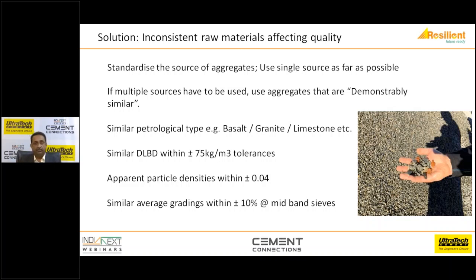If you need to go for multiple sources, I would advise going for 2 or a maximum of 3 sources. Ensure that they are of the same petrological type. The dry loose bulk density should be within plus or minus 75 kg per meter cube tolerance. The apparent particle density should be within plus or minus 0.04. And the average gradings should be within plus or minus 10% in the mid-band sieves. Apart from this, make sure that you don't have a high degree of variability in the 75 micron passing in your crushed sandstone, which is used as a fine aggregate.